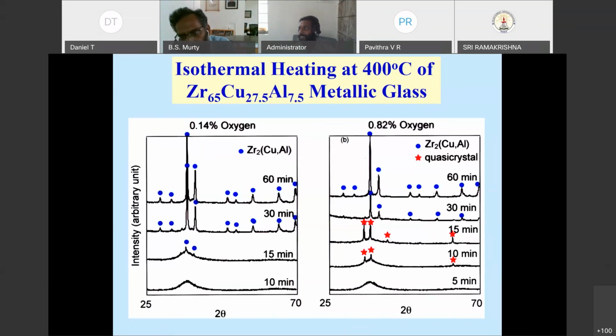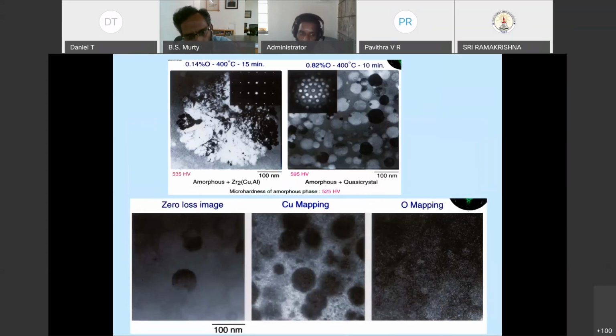And we went to the TEM, went into what is called GIF imaging those days. Those days Titan had not come, and with that, you know, oxygen is a lower atomic number element. So looking at oxygen and seeing that this oxygen is getting concentrated in a quasi-crystal is very difficult to obtain. But what is more interesting is, for example, every one of these circular particles are all quasi-crystalline particles. How do I know? I put my electron beam on each of the particles, get a diffraction pattern, you see the 5-fold symmetry very clearly.